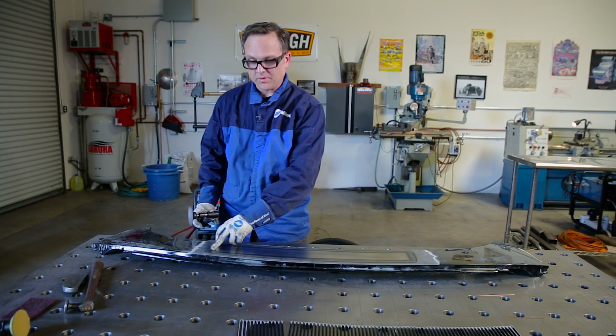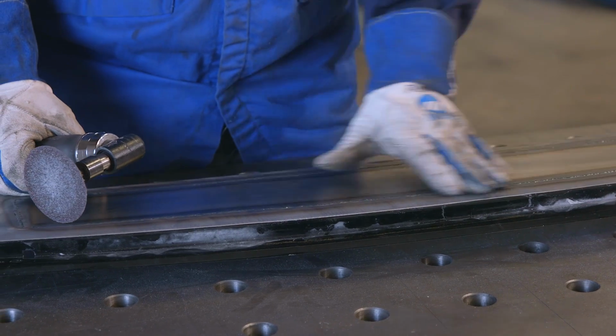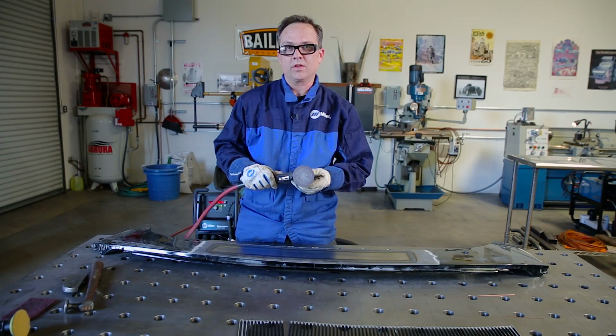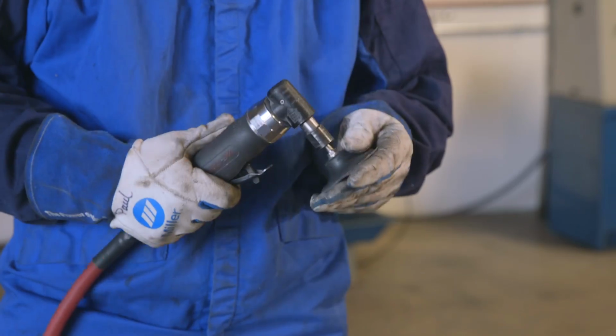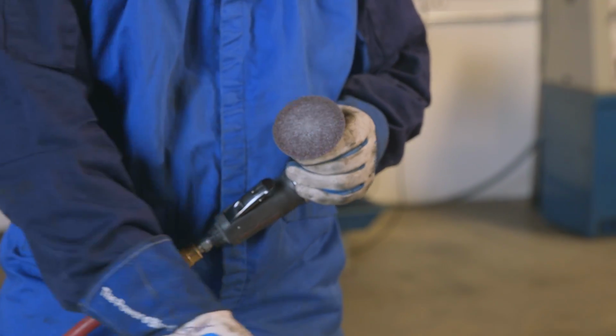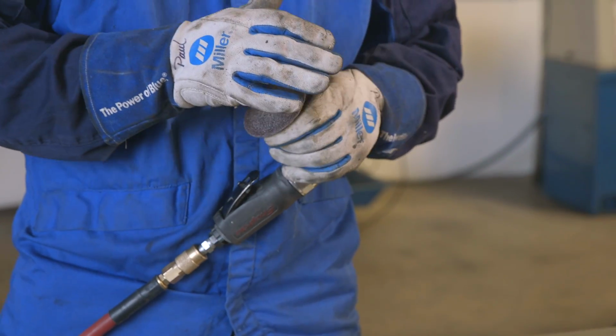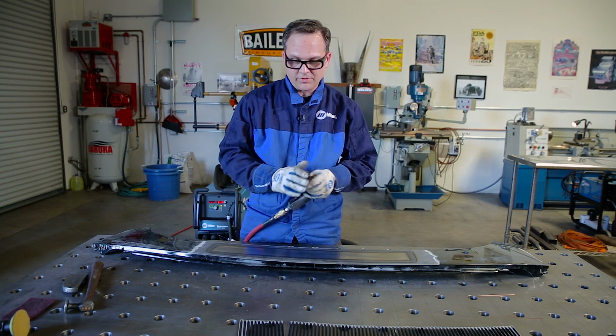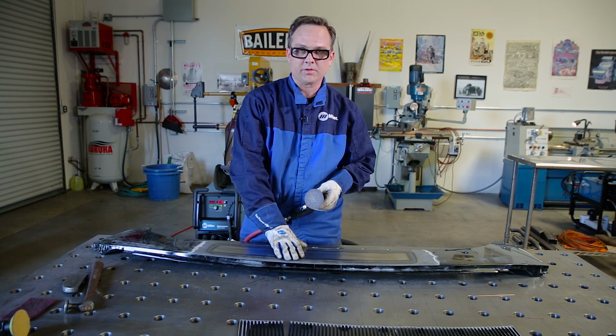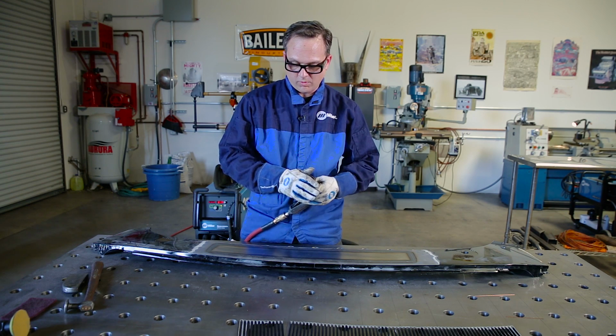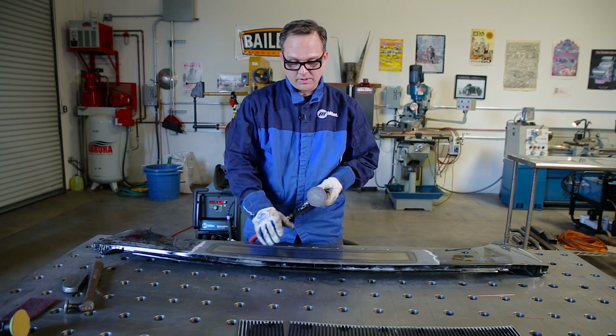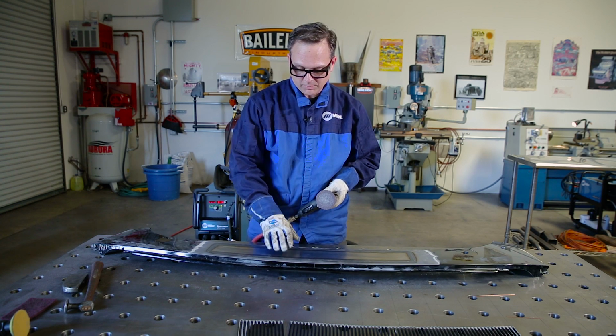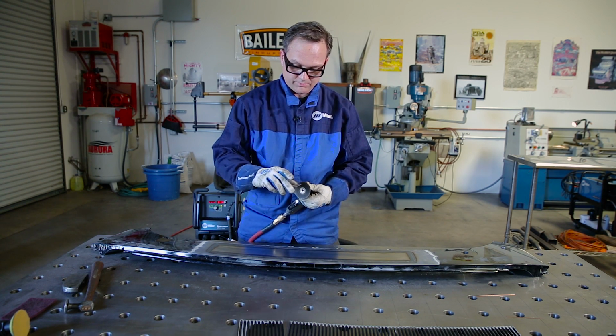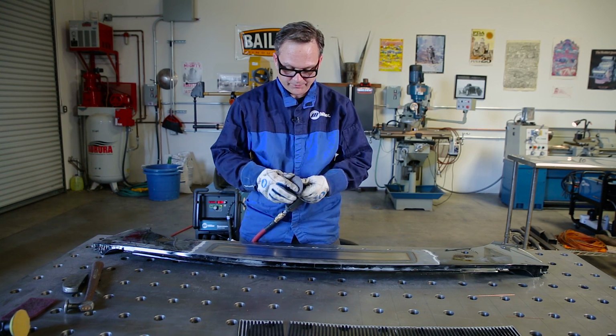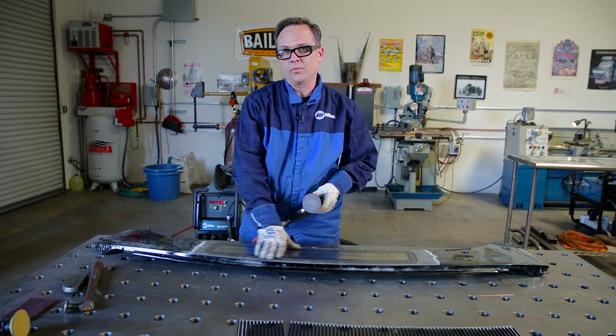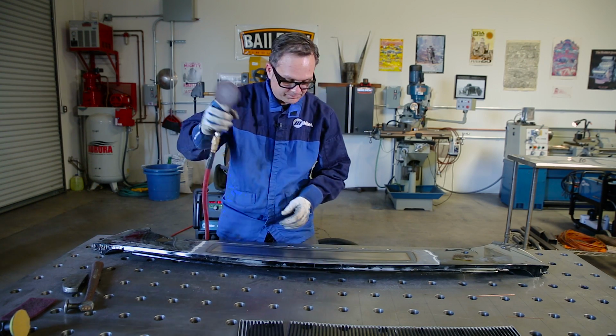Now that I've welded it out completely, I need to cut the top of the weld off, and to do that I'm using a 3-inch disc on a right angle die grinder. It's important when you're sanding something like this to use a good sharp disc. If it's dull, then it will actually heat the material up. It can cause warpage. So you want a good coarse cut first, and then you can step back and use finer ones for a finer finish. But I think I'm using a 36 grit to start, and that'll cut the top of that weld off so that we can planish it back flat.